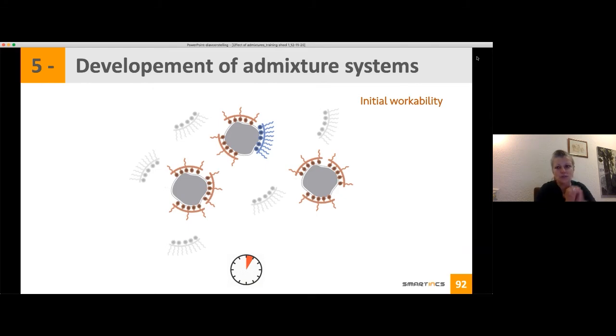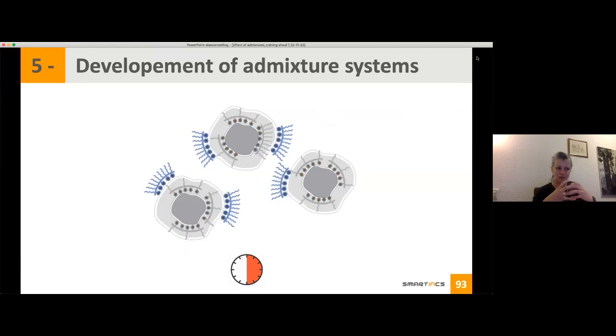And what you can do, you can also combine both of them. So you can use the red one, then you will have initial workability. But because you also want to have retention of workability, you might put the blue one. And it means that when you will have hydration, you still have some PCEs that can adsorb on the hydration layer to still create this dispersion. And then you can really, let's say, target and fine-tune your properties of your admixture. So then you have long open time.